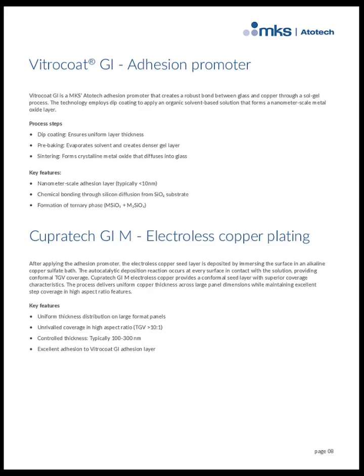VitroCoat GI acts as a nanometer-thin adhesion promoter, forming a strong chemical bond between glass and copper through a sol gel process. This involves dip coating for uniform coverage, pre-baking to densify the gel, and sintering to create a crystalline metal oxide layer that diffuses into the glass. Following this, Atotech deposits an electroless copper seed layer that ensures uniform thickness and excellent coverage, even in high aspect ratio through glass vias. Together, these steps establish a reliable foundation for subsequent copper plating.